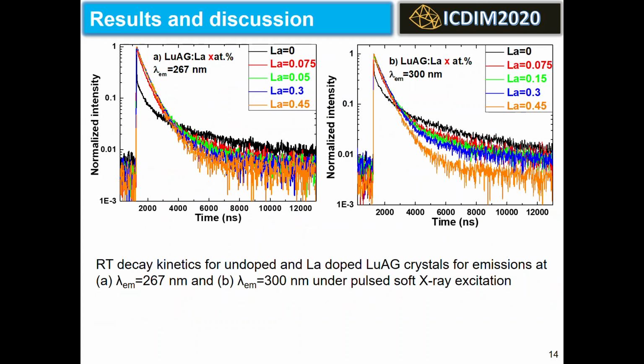This slide shows room temperature decay curves for undoped and lanthanum-doped LuAG crystals for emission at 267 and 300 nanometers, excited with pulsed soft X-ray. Decay curves were recorded at the high energy and low energy sides of the emission band to well separate decay time components coming from lanthanum-lutetium and lutetium-aluminium emission centers.